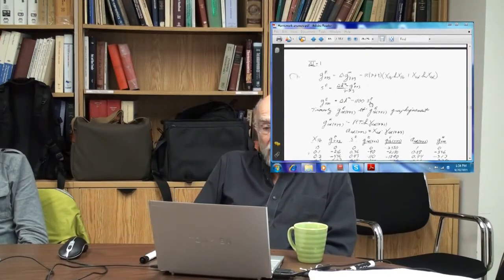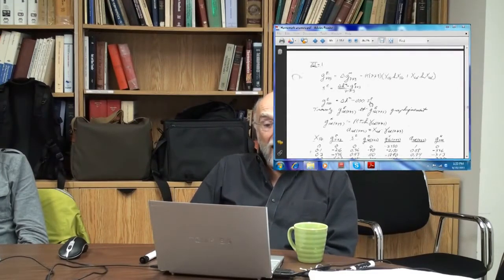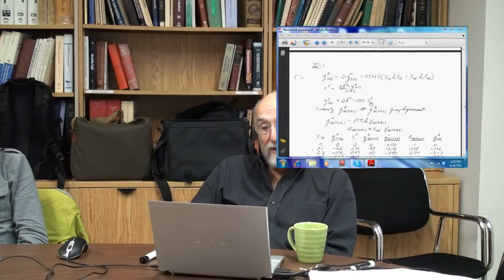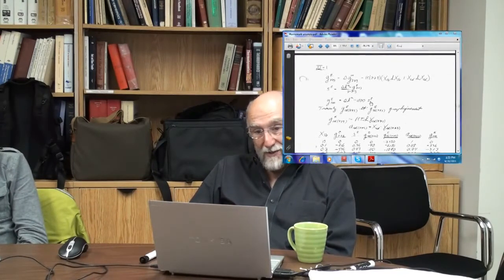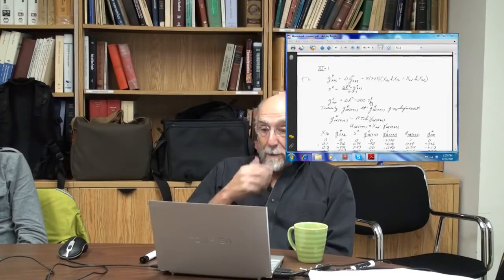By the way, you might prove that for any reaction, delta G is delta H minus T delta S, and from the Gibbs-Helmholtz equation, if delta H is temperature independent, then delta S must be. And if delta S is temperature independent, delta H must be. Either they both depend on temperature, or neither depends on temperature. You can't have one or the other. It's a good exercise to do with the Gibbs-Helmholtz equation.